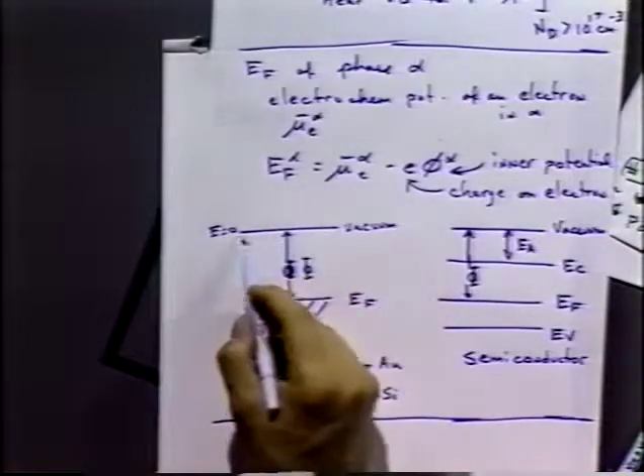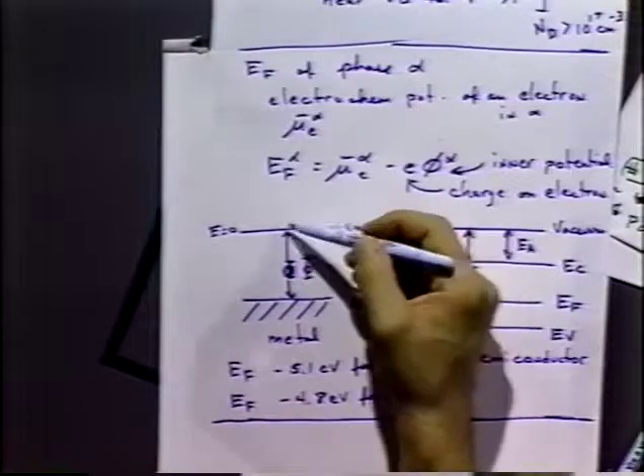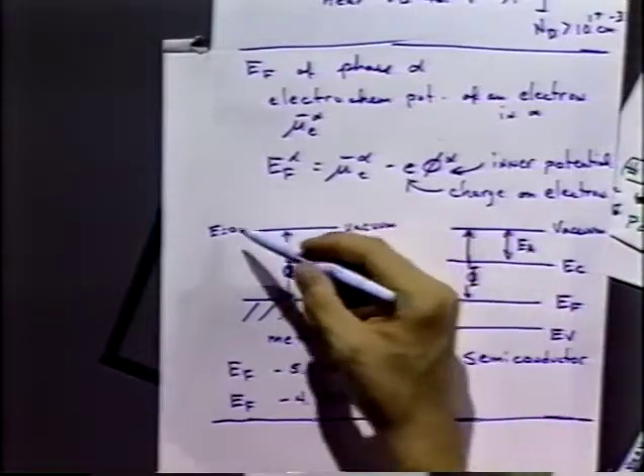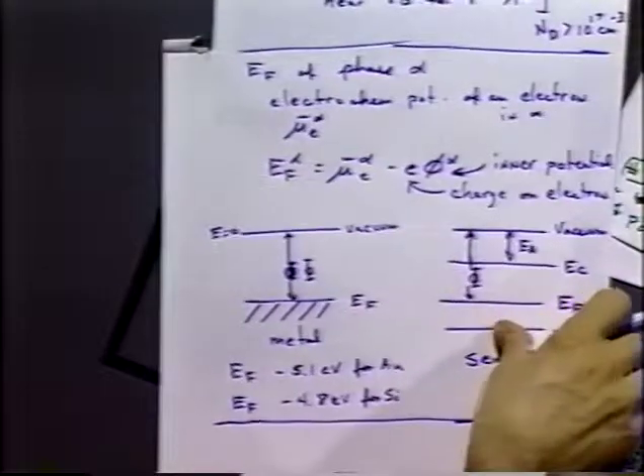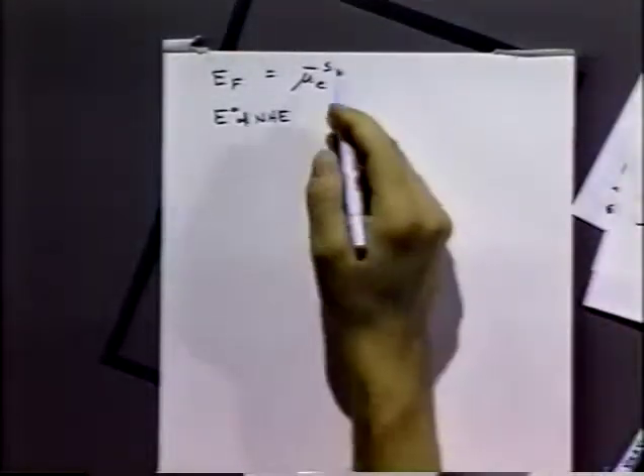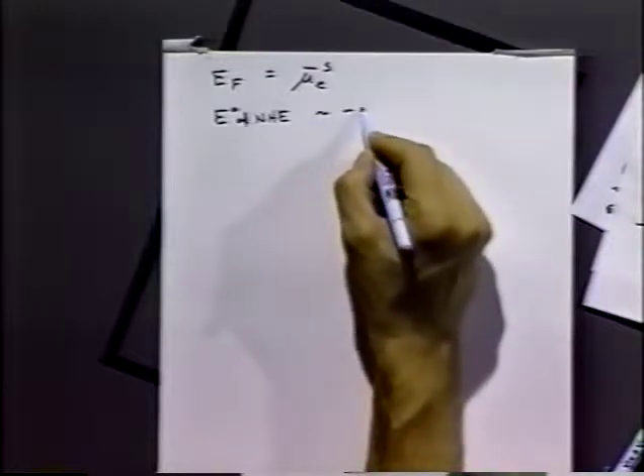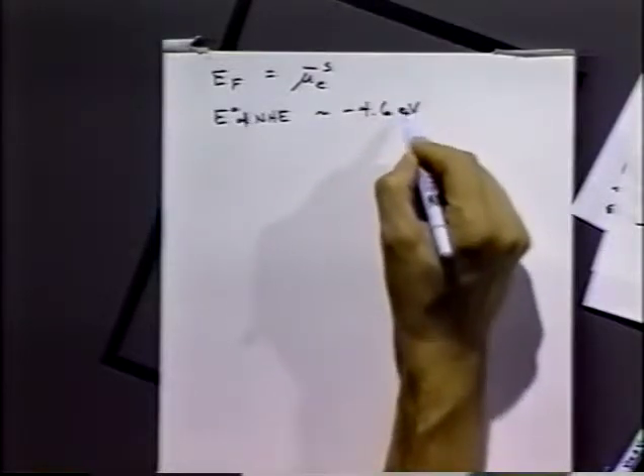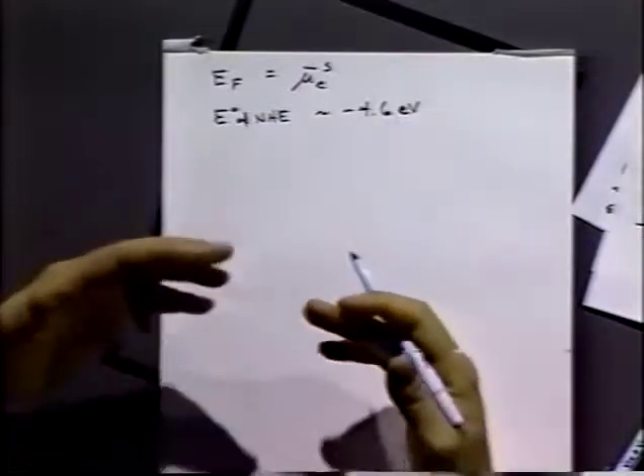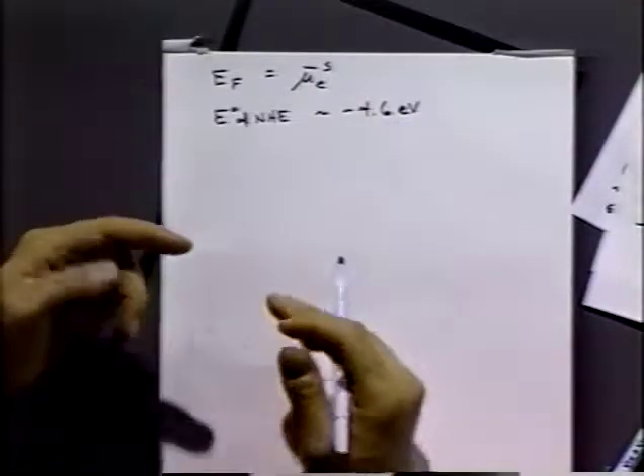Now, you can actually calculate what the E0 of the NHE is when you reference it versus the vacuum energy level. So here we have a vacuum energy level of electrons in the system. So what energy level is the NHE on that scale? What's the energy difference between the electrons in the vacuum and the electrons' energy at the NHE E0? Well, it turns out if you calculate it, it is approximately minus 4.6 eV. So as you'd expect, the electrons, again, are more stable in solution in the NHE system than they are in the vacuum. We don't have electrons being sputtered off in the vacuum from our system.